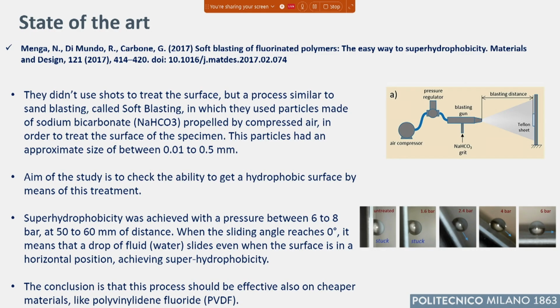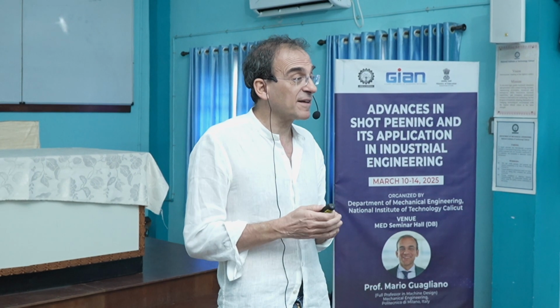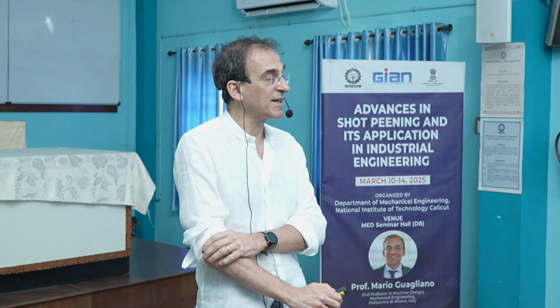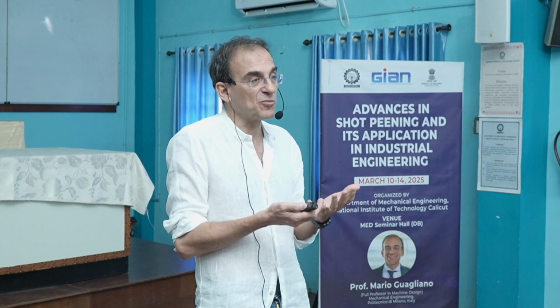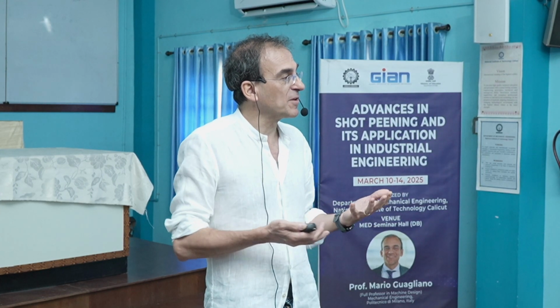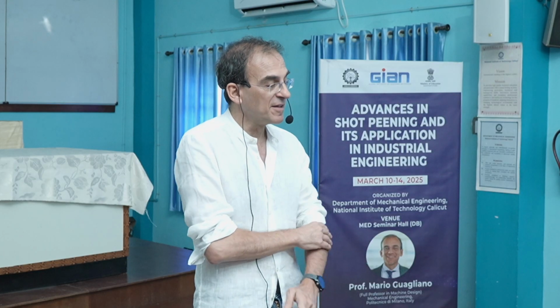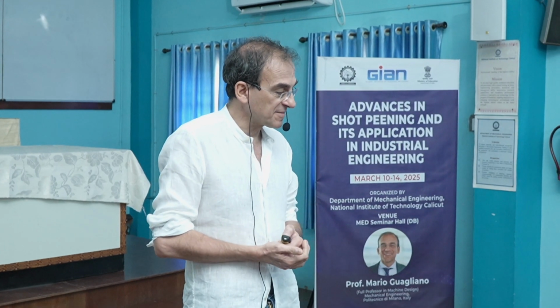By considering the different combinations of parameters they tried, they were able to obtain, as you can see, a super hydrophobic surface. That is to say, if a drop of water is put on the surface, the water is not spreading along the surface, but remains self-contained with an angle with respect to the surface that is larger than 150 degrees. This is a super hydrophobic surface. This is interesting because many treatments used for obtaining a similar result induce chemistry and chemical processes. In this way, this seems to be a quite simple process if we wish to obtain a surface behavior like this.